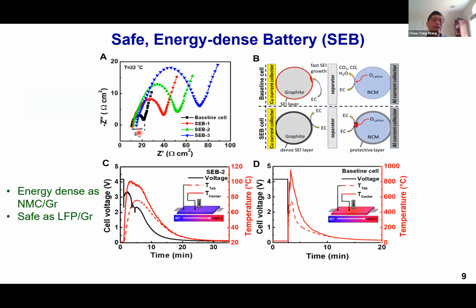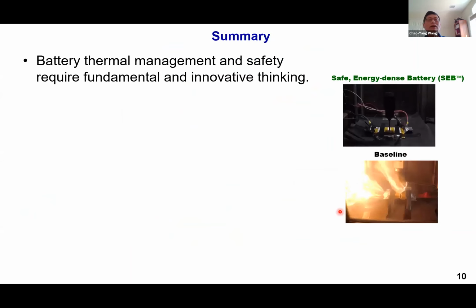It's very safe, and you can see that the black curve is the internal or charge transfer resistance baseline, and all those other colored ones are the SEB batteries, and we see much larger charge transfer resistance. So sometimes highly resistive batteries are very good for safety, and indeed, if you do nail penetration, for SEB batteries the highest temperature rise is only 100 degrees Celsius versus almost 1,000 degrees Celsius for the baseline. So we could achieve a battery that is as energy dense as NMC graphite, but as safe as LFP graphite. Okay. So very quickly, I'm putting a summary here since I'm running out of time.